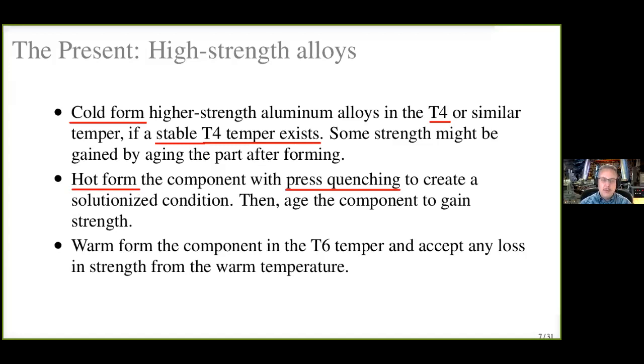Now, this is a problematic process for a number of reasons. One is that when you take the material up to that high of a temperature, handling a sheet of it is like handling well-cooked linguine. It wobbles all over the place. You have all kinds of problems with potential distortion. The next problem is you have to have the press quenching the part rapidly enough for some of these quench-sensitive alloys. So that's a real issue. You're pulling a lot of heat into that die set, and that's going to limit how many parts you can process per hour, because the dies will simply heat up and not be effective quenchers anymore. You also have the problem with uneven quenching. So it's a tough process to make work. People are trying to do that right now.